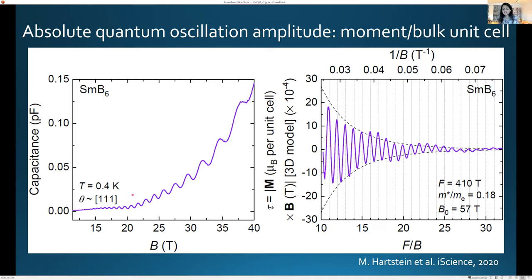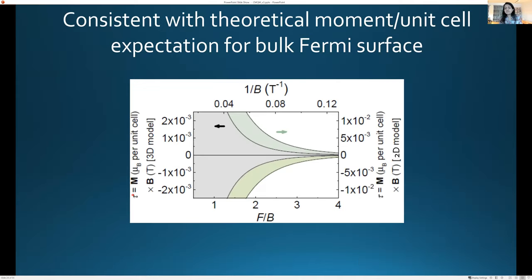And that's reasonable when you look at, if Lifshitz-Kosevich theory were to hold, if you take a theoretical estimate and say, okay, for this size of Fermi surface, what would you expect for the Bohr magnetons per unit cell? And you would expect about 10 to the minus 3. So at least, within less than an order of magnitude, it's reasonable. And this is regardless of the geometry of the Fermi surface. If it was more like a sphere, if it was more like a cylinder, you would still see about 10 to the minus 3.